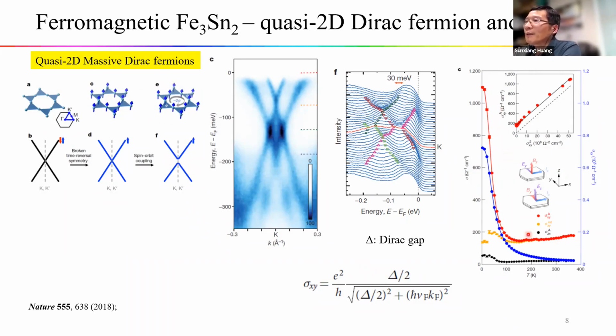So here shows the anomalous Hall conductivity in these materials. For the field along the c-axis, the anomalous Hall conductivity is relatively large and increases at low temperature. But for the field in the ab plane, the anomalous Hall is much smaller. The comment from some theory suggests the observed intrinsic anomalous Hall comes from this Dirac gap, and the value depends on the gap value.